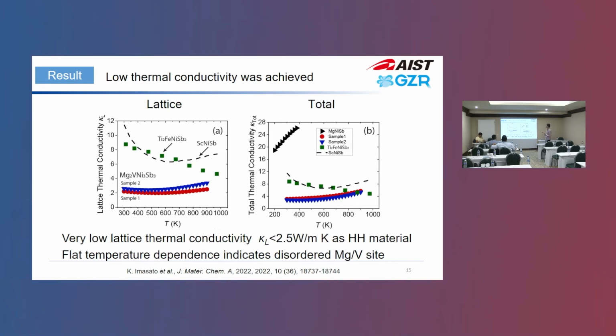And more interesting, the thermal conductivity is much lower, as we expected. Actually, this is a completely disordered structure, so we don't think this is because of the expansion of the unit cell, but probably just because of the disorder on the magnesium vanadium site. The lattice thermal conductivity goes to almost 2.5, which is much smaller than the parent material, scandium nickel antimony, which is more like 10, 12. And this double Half-Heusler composition reaches 3 or 4 at higher temperature, but it's pretty flat because it's alloyed, disordered. Just staying at 2 or 3 is pretty low for Half-Heusler compositions.